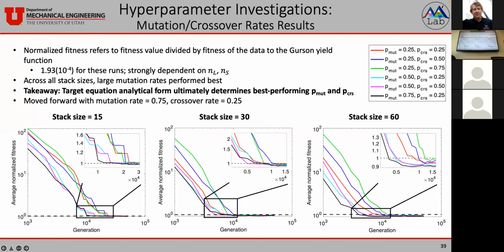Okay, so here are the results. First off, I'm showing the mutation and crossover rate results. Before I jump into the figures, I'll define normalized fitness. This refers to the fitness value divided by the fitness of the data to the Gurson yield function. For the training data set used for this investigation, this was about 10 to the minus 4. But again, this is strongly dependent on the specific data set, so again, dependent on NL and NS.